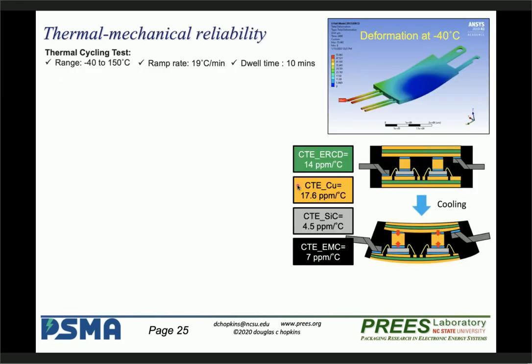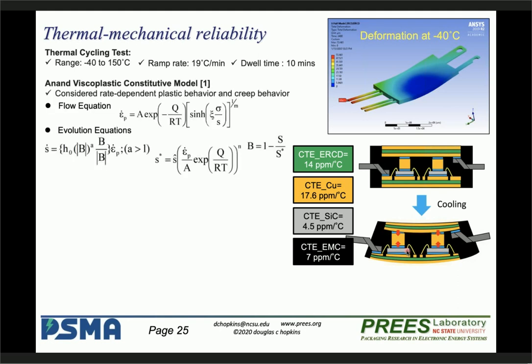Okay, so in addition to the thermal modeling, I also did the thermomechanical modeling for characterizing the reliability in the thermal cycling test. So here are the conditions based on the JEDEC standard. On the right side, it shows how CTE mismatch induces the thermal stress. For example, in the low temperature stage, copper spacer would shrink more than the epoxy molding compound, the black material here. Therefore, it can cause a die crack or solder layer delamination. In the simulation, I applied the Anand viscoplastic material model for considering both plastic and creep behaviors in the solder material.